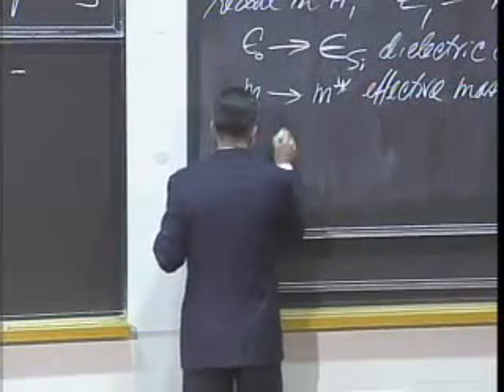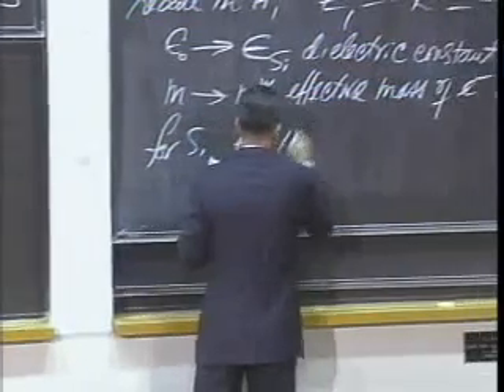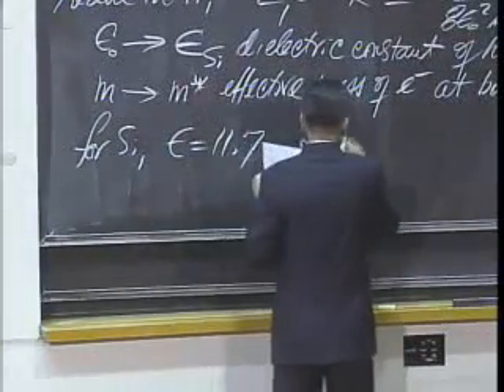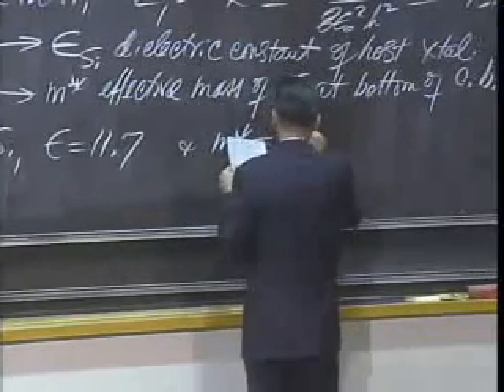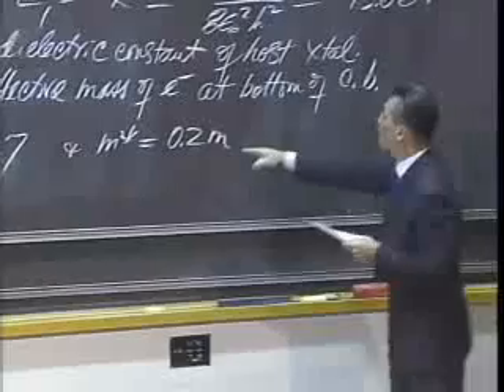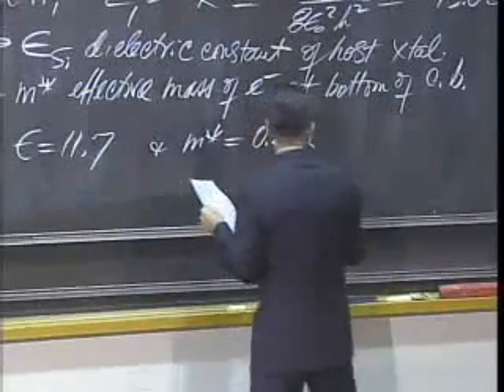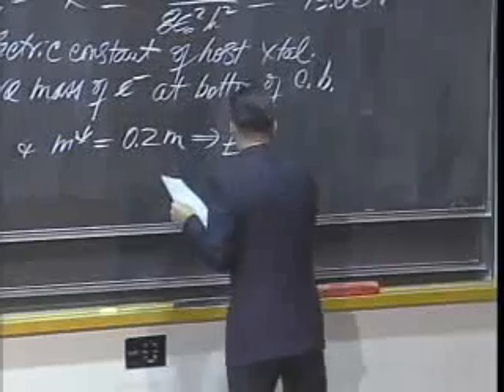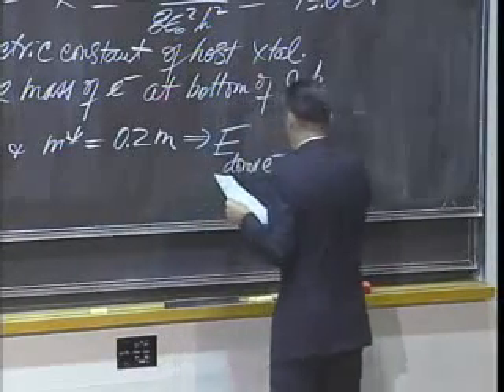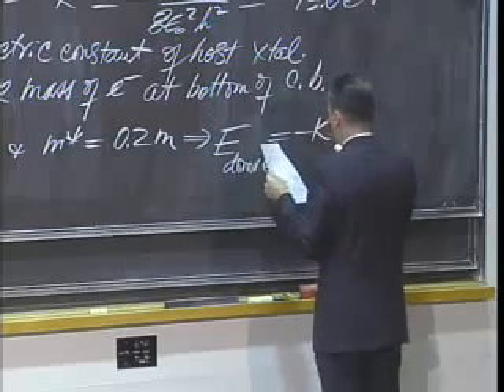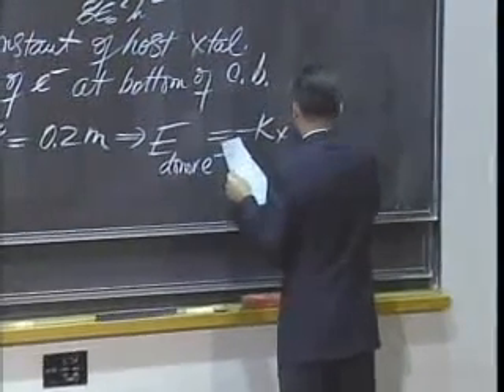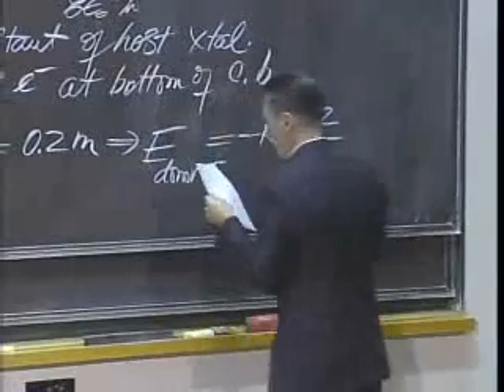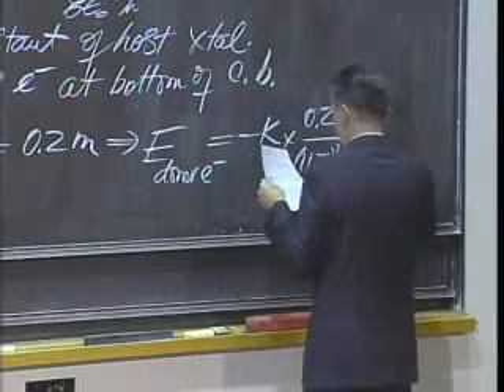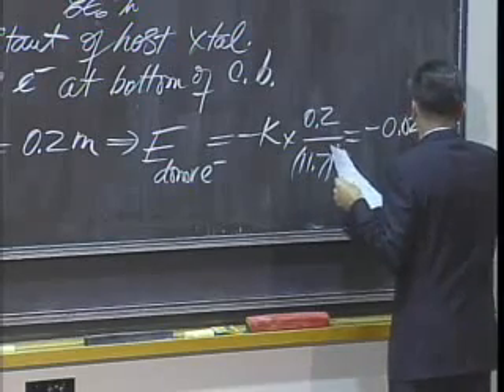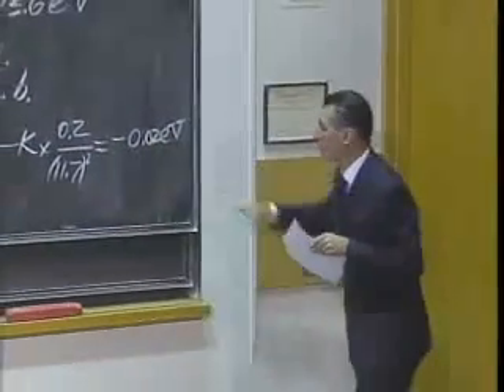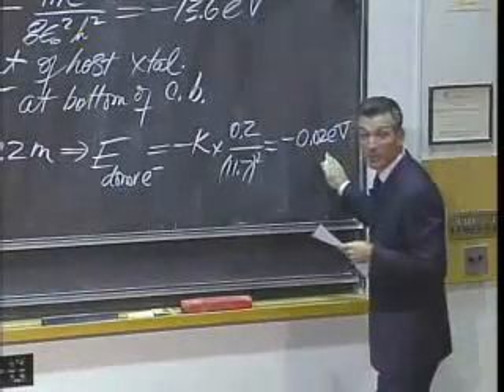For silicon, the dielectric constant is 11.7, and the effective mass at the bottom of the conduction band is 1/5 of the rest mass. So I'm going to plug these values into this equation, and what this gives me is that the ground state energy of the donor electron is minus K, as we had before, multiplied by 0.2 on the top, and then I'm going to have an 11.7 squared on the bottom, and that gives me minus 0.02 electron volts, 2/100ths of an electron volt. This quantity has been measured.